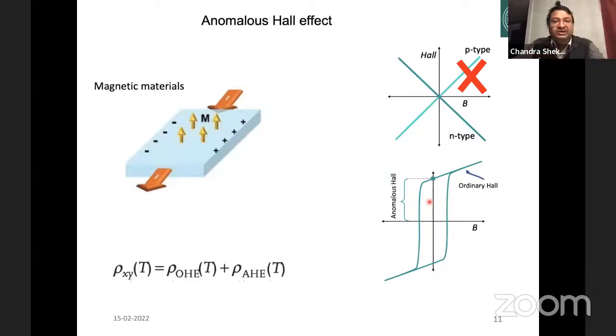When you switch off the magnetic field, we still have a Hall voltage, Hall resistance. Such a non-zero voltage we call the anomalous Hall resistance. But we also have an ordinary part like here. The ordinary part can give us the ordinary physical properties of the material, the same as charge carrier density, mobility and type of carrier, which we can measure.